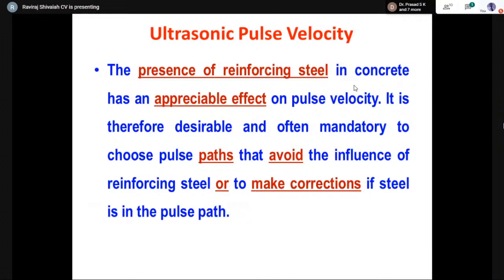And the most important part is the last one that I'm trying to tell you here. The presence of reinforcement steel in concrete, which is inevitable, will have a real appreciable effect on pulse velocity. So it's very desirable to keep your transducers at places where it is relatively free of, or farther from, the reinforcements, because it's going to really affect the pulse velocities. In case it's not possible to have a place quite far from the reinforcements, you need to know where the reinforcements are, at what distance they are, and the alignment of the reinforcements.